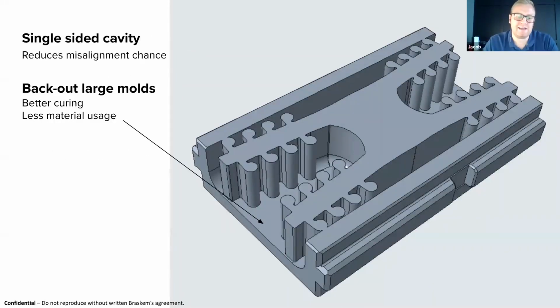And then on the other side of the cavity, these are things that you normally don't really think about with metal molds, but you have the opportunity to control them here in a 3D printed mold. Backing out of large molds can help. These molds are made from curing materials. So whenever you get very thick cross sections of the mold, you can actually have a difficult time curing a very thick inner part of that mold. So we used a technique that helped a lot, what I call backing out.